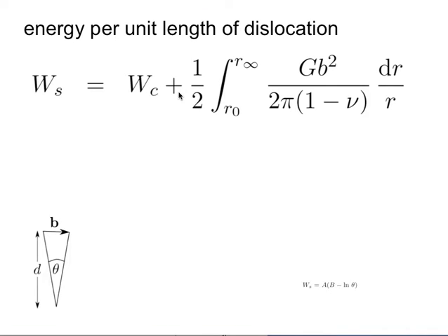Okay, now the next thing to do is to work out the energy of that interface. We've got the energy of a dislocation per unit length. You familiar with this equation? What does the term W_c stand for? You know, you divide your dislocation energy into two parts. One is due to the elastic strain field, and the other one due to the core. The elasticity theory doesn't apply to the region very close to the center of the dislocation, right? Because the displacements are large. So that's called the core energy.